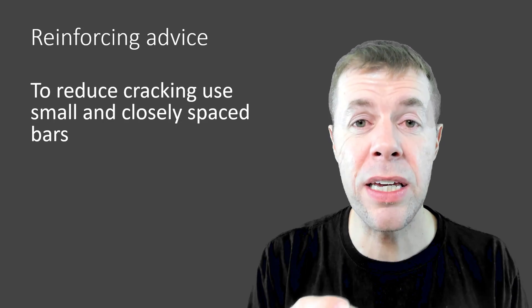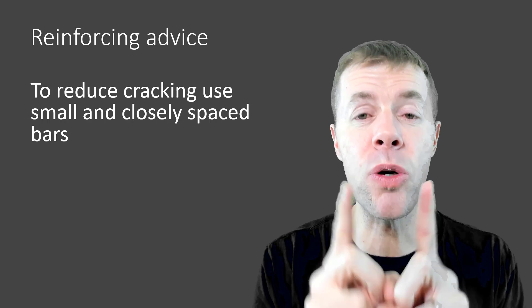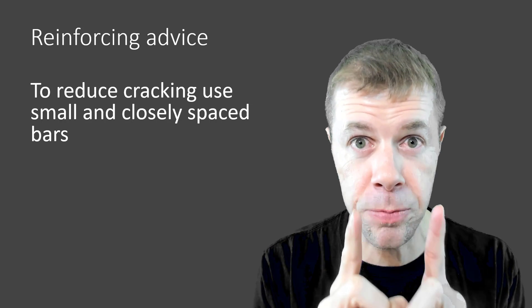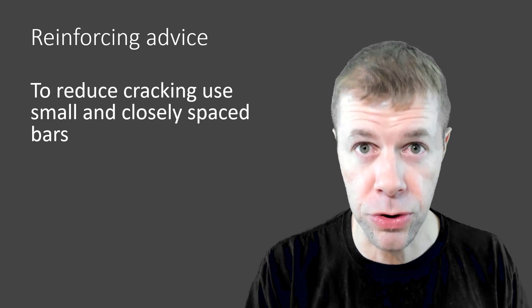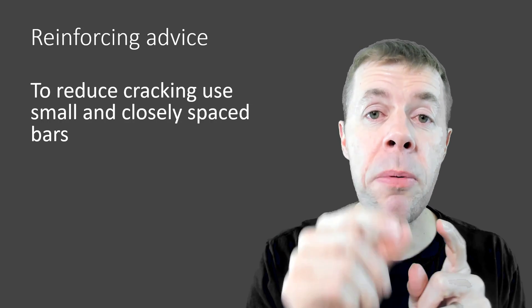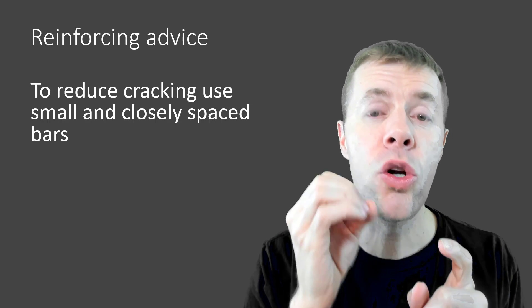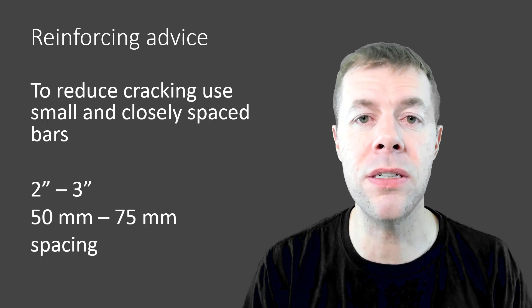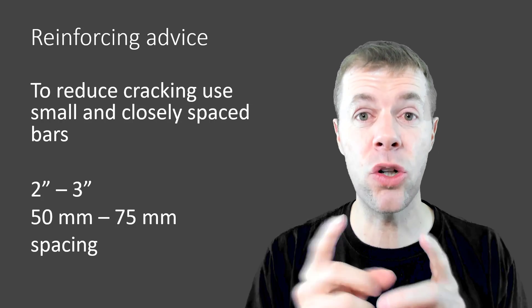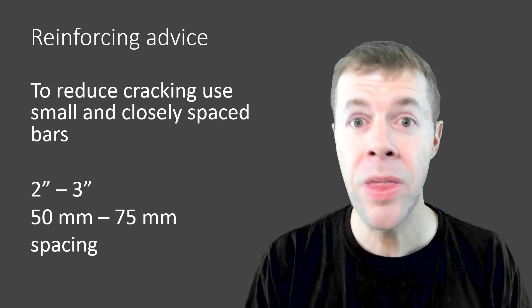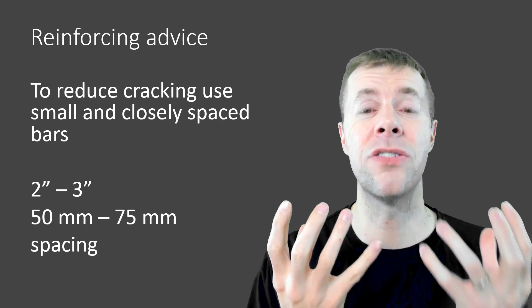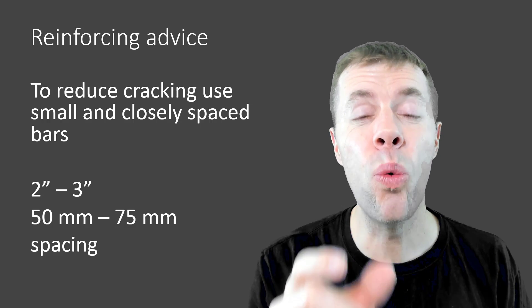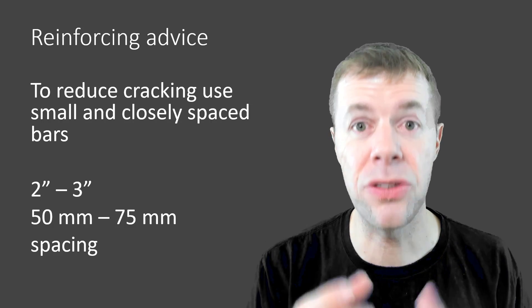To reduce cracking, it is a great idea to keep your rebar as close together as you possibly can. You don't want to get them too close though, because you need to be able to get your aggregate in between them. Typically two to three inches is as close as you can possibly get them. That will help minimize cracks.